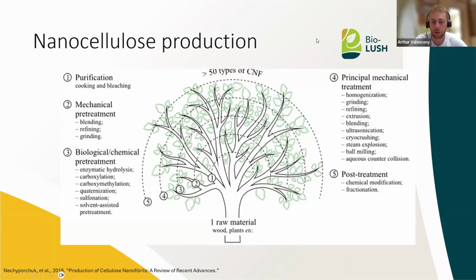And I just added this slide to show that from one raw material, there are different steps to produce nanocellulose, starting from purification, meaning cooking and bleaching, and then we can introduce a mechanical pretreatment to improve the production of nanocellulose. We can also introduce a biological step with enzymatic hydrolysis, for example. And then finally, the mechanical treatment that can be of different natures, starting from homogenization, grinding, refining, extrusion, and so on. And also some post-treatment to improve or add properties to these cellulose nanomaterials. So with all these different steps, we can obviously have many different kinds of cellulose nanofibers, with more than 50 types, for example.